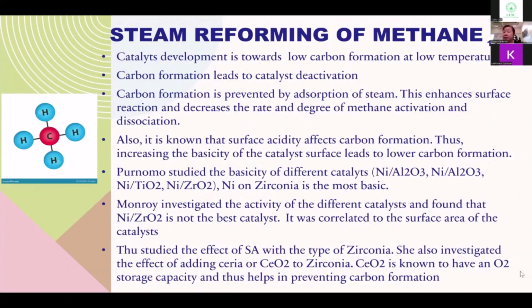The reaction is industrially operated at a high temperature of around 800 degrees centigrade over nickel alumina-based catalyst. Such high temperature causes some demerits, including the expensive tubular reformer made of high alloy nickel chromium steel, irreversible carbon formation in the reactor, and the large energy consumption. The lowering of temperature, however, may lead to lower conversion and increase in carbon deposition on the catalyst, thus causing the unwanted deactivation of the catalyst. The development of catalysts for steam reforming is based on the key problem of avoiding the formation of carbon. In recent years, progress has been reported, resulting in better control of carbon limits and better catalysts.